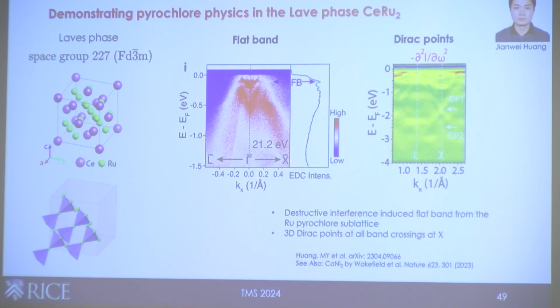And so this is a heroic effort. You can cleave like 30, 40 crystals, maybe get one good region to measure. This is what we do as experimentalists to try to find the interesting stuff. So we did the measurement, and you can see portions of a flat band with a peak here, near the Fermi level. And then the second feature is that if you look for the Dirac points at the X point, you can see features that are Dirac points here, which are protected by this non-symmorphic symmetry. And also see the reference of this calcium nickel-2 material of the same structural family from Zhou's work.